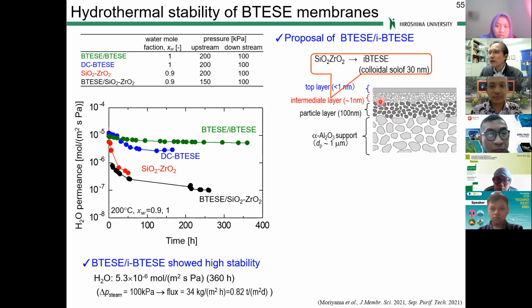This i-BTESE layer is stable. BTESE itself is stable, okay? Silica zirconia decreases the permeance. This also decreases. So the difference is that this BTESE coated on i-BTESE is now stable. The difference is this intermediate layer. The top layer is the same.